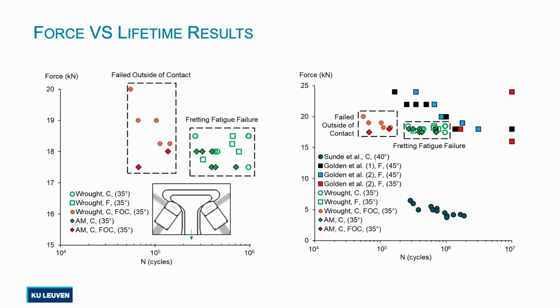When we say outside of the contact, it's in the transition area, and mainly in this neck area. So for the wrought material, we could explain it, because according to the finite element model that we had, if we apply higher stress levels, then we are not having the most damaging contact situation, and the stress shifts to the neck. I will show you a graph later, and I'll explain why.